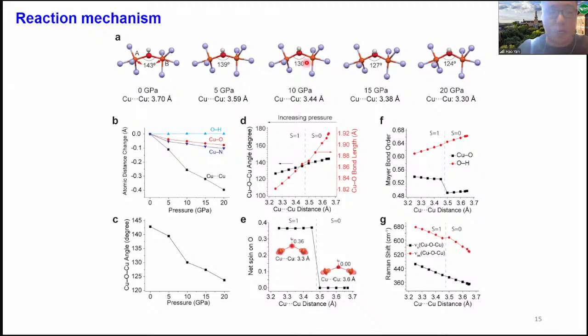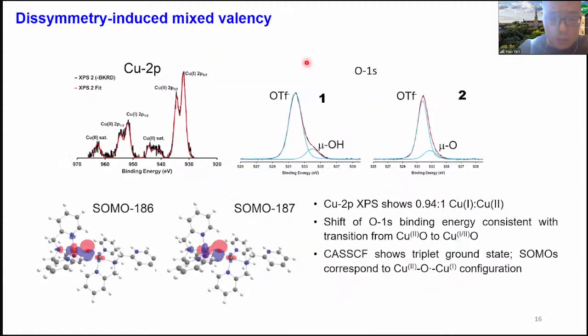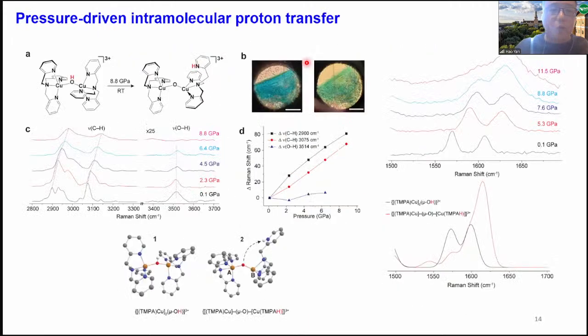We can analyze this by looking at atomic distances and charge distributions, as well as spin states, which I would not go into all the details. But as we have found, probably the most striking thing about this is that this proton transfer is not electronically innocent, let's say that way. We started off with a compound with two copper-2 centers, and after this transfer, you see that the two coppers now sit in different ligand environments.